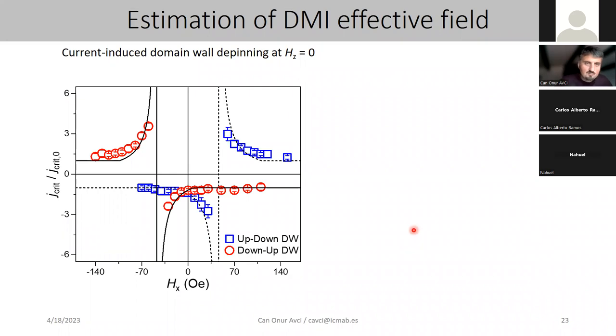So this is what we did here. As you can see, when we plot the critical current to start moving the domain wall in the presence of an in-plane field, we saw that there is a divergence at negative 50 Oe in the case of the down-up domain wall, and a divergence at positive 50 Oe in the up-down domain wall. And this is explained like here, basically.